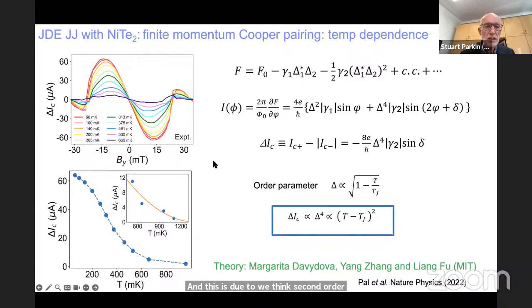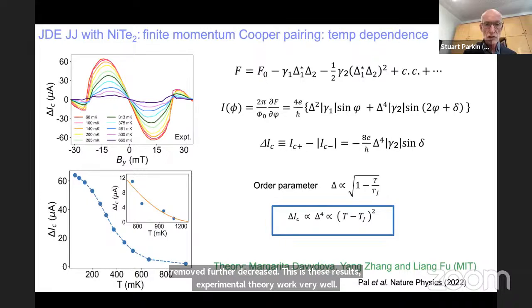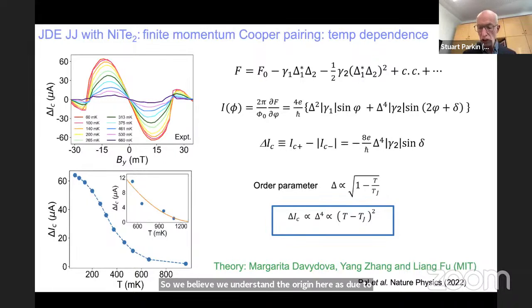And we can explain then this field dependence in this way, and in particular, the temperature dependence, which in this case, as you reduce the temperature away from the ordering temperature of the nickel ditelluride, increases as a product quadratically with the change as the temperature is further decreased. Well, these results, experiment and theory, work very well, so we believe we understand the origin here as due to finite momentum Cooper pairing, similar to the result for a ferromagnetic superconducting interface.